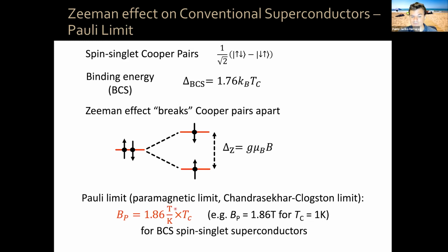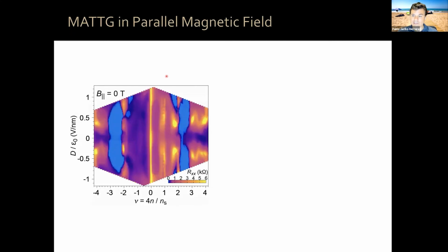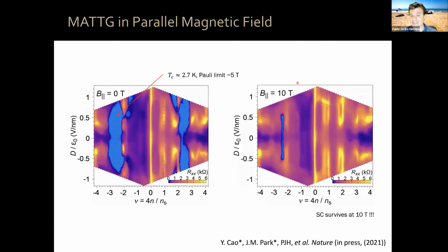This is known as the Pauli limit, which is about 1.86 Tesla for a 1 Kelvin superconductor. This is again for BCS spin singlet superconductors. Now, we take our magic angle twisted trilayer graphene samples, we warm them up, and we rotate them so that they are in a parallel magnetic field. We measure again, and you can see a very similar diagram as before, with a TC of 2.7 Kelvin here. The Pauli limit is 5 Tesla. So by the time you apply a 5 Tesla parallel field, superconductivity is long gone. You apply 10 Tesla and you can see that the system still superconducts in an extended region.